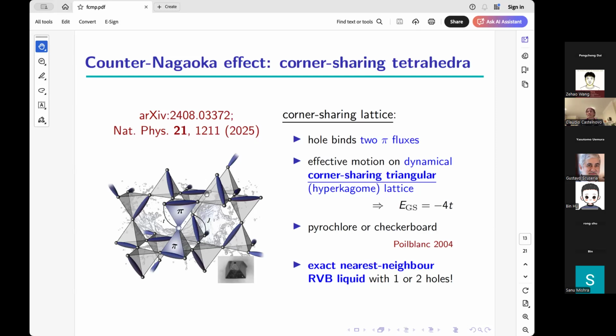And the embedding is completely dynamical because as the hole moves through, it moves around the singlets, and therefore it changes the triangular lattice over which it moves. But at any instantaneous point where the hole is somewhere, the hole is able to hop around two triangles and therefore has connectivity 4. Right? There's 4 directions it can hop in. And therefore, lowest energy is minus 4t, exactly. Not approximately, not with a correction, it's exactly minus 4t. The singlets next to the hole again do the same trick of attaching a pi flux to that triangular face and allowing it to gain the full kinetic energy without any corrections.